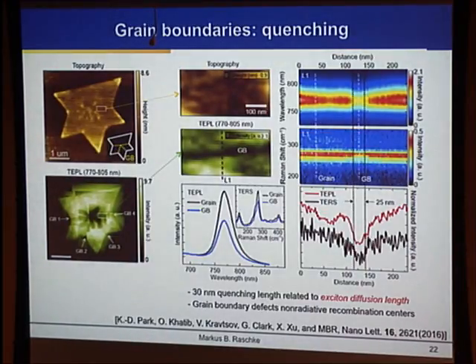So this is not a trivial result of a change in the band gap and differences in the photoluminescent yield as a result of the gap size. But this 30 nanometer quenching corresponds to the exciton diffusion length at room temperature. So what this tells us is that the grain boundary defects, which are atomic scale, very localized, as one knows from transmission electron imaging, really act like non-radiative recombination centers.